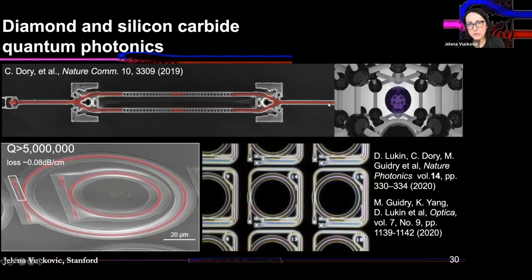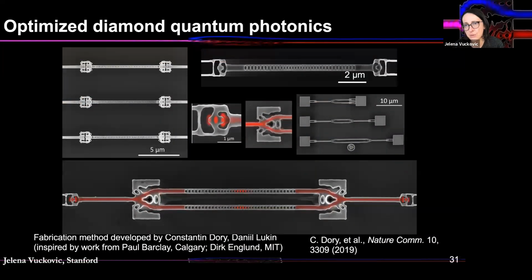So what we do is three-dimensional bulk carving for diamond, and literally we carve out these structures that are suspended in diamond, and you see some inverse designed elements there. And we do it in such a way that we etch down and then undercut sideways and still keep color centers inside. And in silicon carbide, what we do is basically we make silicon carbide on insulator ourselves and then make photonics. And I'll show you some of the recent results in these materials that are quite exciting.